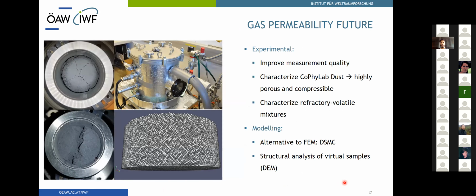The findings from the initial experiments and simulations will be used to improve the measurement quality for future experiments. One example I already showed, which is the redesign of the sieve. Another example would be the replacement of older pressure sensors with newer, more accurate ones. One of the challenges for future measurements is to characterize materials such as the Cophylab dust. As it is highly porous and compressible, it is very difficult to analyze without altering its structure. These images show how the sample shrinks and forms fractures when the chamber is evacuated. To mitigate this problem, we are installing a needle valve that allows us to evacuate the chamber more slowly.